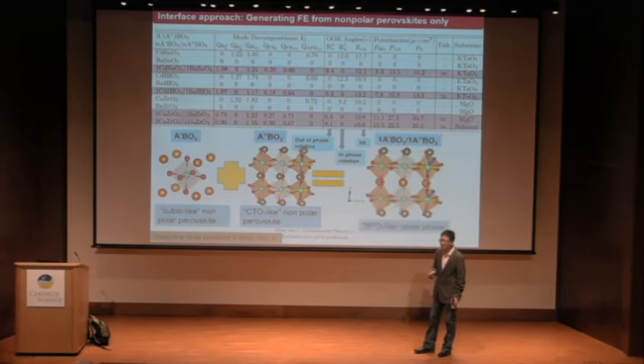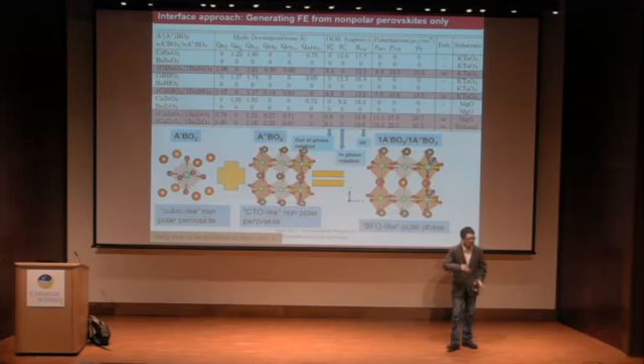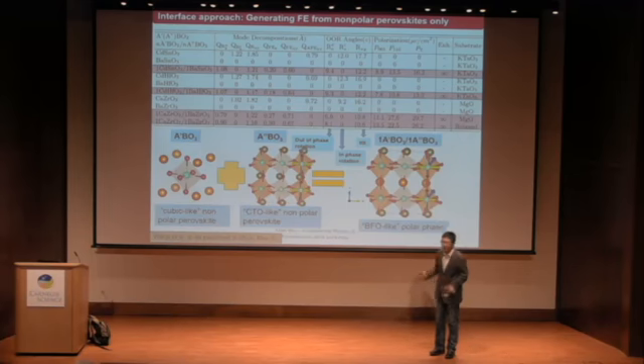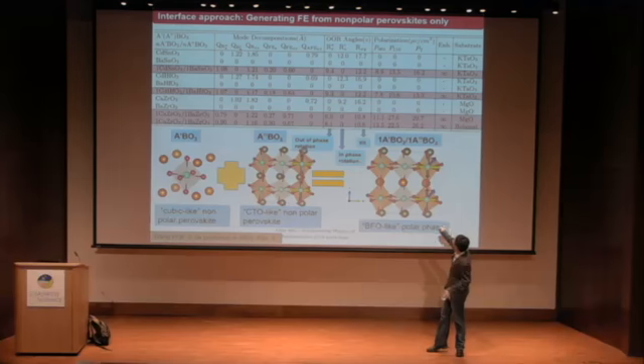Then you combine these two together to make a 1x1 superlattice on any substrate. We can see that the rotation pattern changes. We get out-of-phase rotation coming out with tilting, and the in-phase rotation is completely gone.